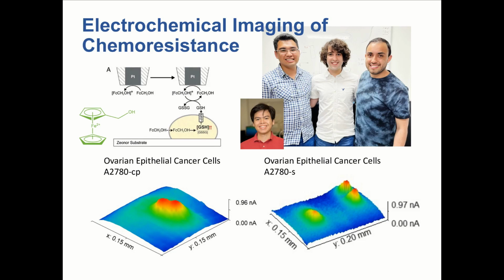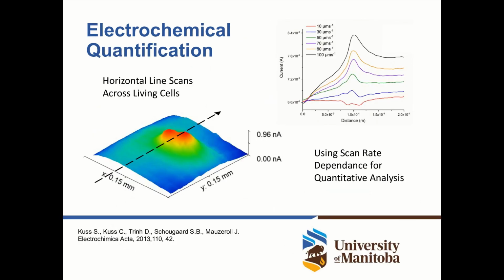We do this for ovarian cancer cells that are resistant to a chemotherapeutic called carboplatin. Carboplatin is one of the most widely administered chemotherapeutics across different types of cancers. And we have cells on the right-hand side that are susceptible to carboplatin. But how can we now quantify the resistance phenotype of these cells? When we scan over the cells, which is indicated by this arrow, we can carry out these line scans at different scan rates. And when we do so, we get an increase in electrochemical current, shown here on the right,